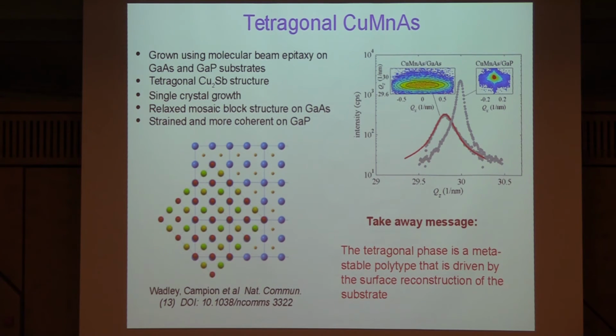This is the material. Basically grown using MBE on gallium arsenide, or actually now on gallium phosphide quite a lot. It's tetragonal copper manganese antimony structure. Relaxed mosaic blocks, you can see actually from the wide full width half maxima here and the quite broad spread in reciprocal space. And you can also see that it's much more strained and coherent on gallium phosphide, much tighter, much smaller full width half maxima.